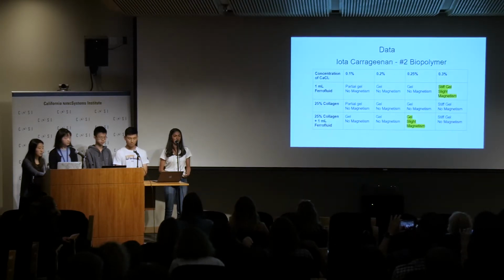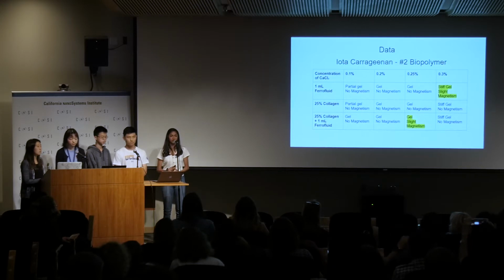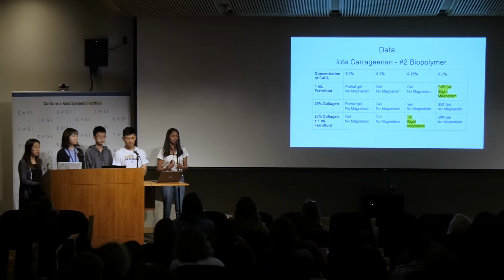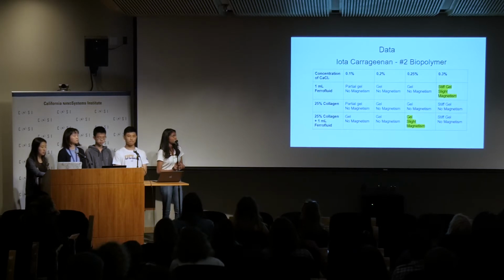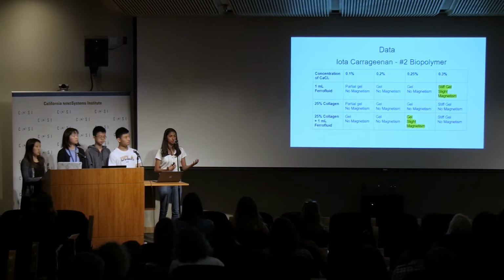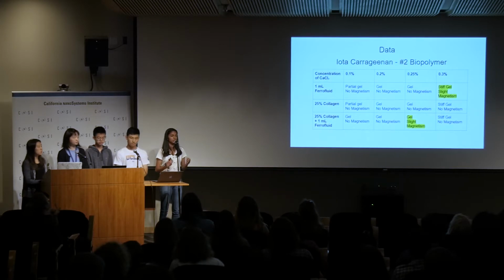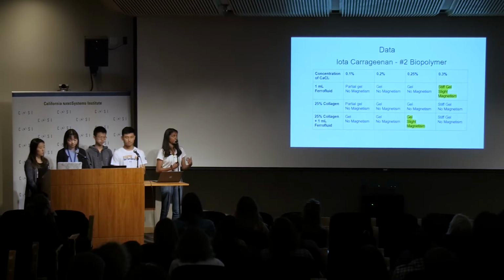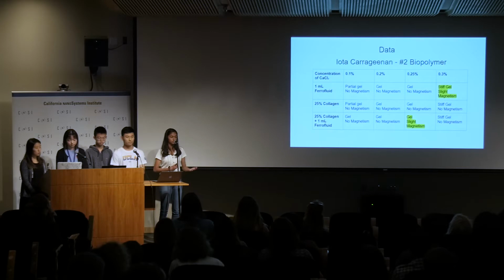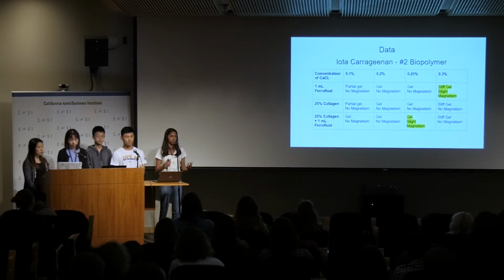So moving on to the second biopolymer that we tested, the one that we did previously last week, which was iota-carrageenan reacting with the calcium chloride. So calcium chloride is actually the cross-linking agent for iota-carrageenan, and we did 4 types of concentrations for the calcium chloride. So basically, we would have a constant for the iota-carrageenan, which was 1%, and then we had a variation of the CaCl2 concentration. So we would heat up the entire solution and then we would cool it, and that's how the gel would be created.